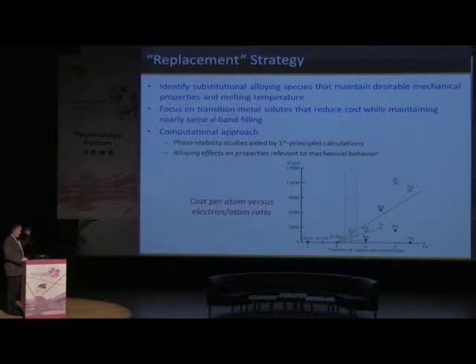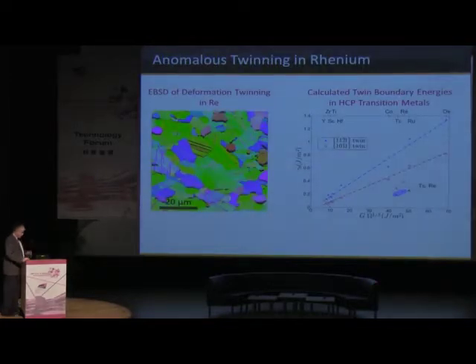But now what about ductility? Now the risk is that if we start making alloys that are cheaper, they're going to end up being very, very brittle. Okay, so this is using high throughput computation in kind of a different way. It's more thinking about things on more of a mesoscale. So one of the things we know about rhenium is that if you deform it at low temperature, it has a lot of these twin boundaries which form. So these different colors in this micrograph, electron backscatter diffraction, are twin boundaries. And this material twins extremely easily.